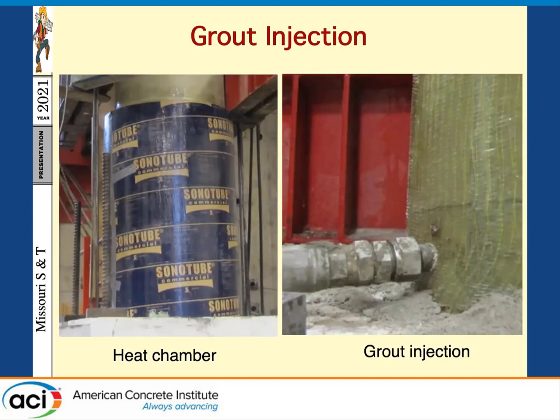So in total, the total repair time was about 6 hours: 1 hour for wrapping the glass fiber, 4 hours heat curing, and then 1 hour for the grout injection. And then after the 6 hours, the column was very much ready for testing.